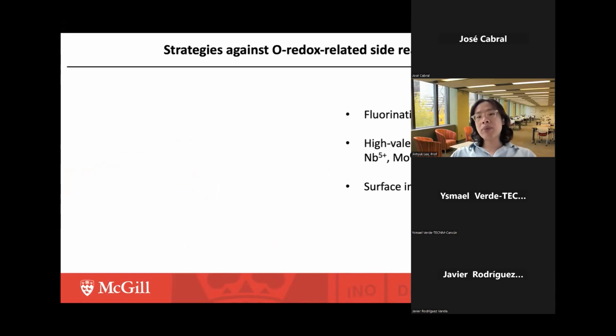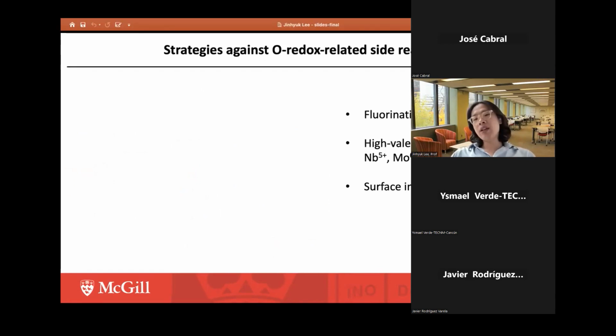So based on this understanding, I tried to come up with some strategies to prevent this oxygen redox related side reaction. I came up with several different strategies, including fluorination, which means that you replace some of the oxygen 2 minus anion with the fluorine 1 minus anion. So we call it fluorine substitution for oxygen, or fluorination. And this is one strategy. Another strategy is called high valent cation substitution. Here, the high valent cation is niobium 5+ or molybdenum 6+. So the oxidation state of this metal is simply high, so we call it high valent. And finally, I also studied the so-called surface immunization. It's a treatment to passivate the surface against oxygen redox related side reactions.